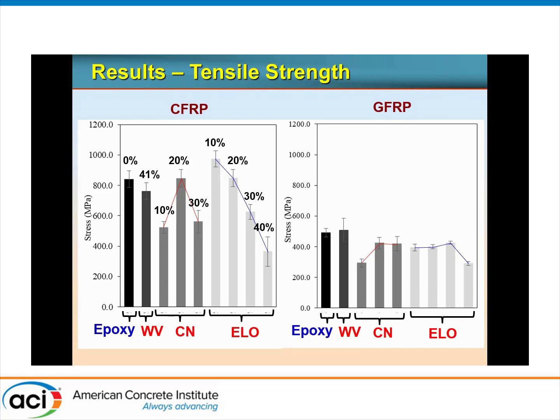So these are the results here. You see here is the epoxy, that's the carbon and glass, that's the epoxy, typical tensile strengths, and that's the WV, which is 41% bio. So these are the percentage of bio. And now that's the second type here, going from 10% bio to 20% to 30%. So clearly, within the limitations of this study, it appears that the optimal was 20% in terms of the highest